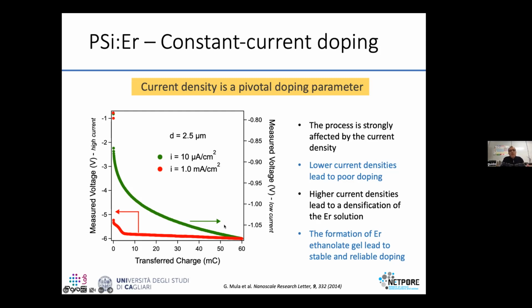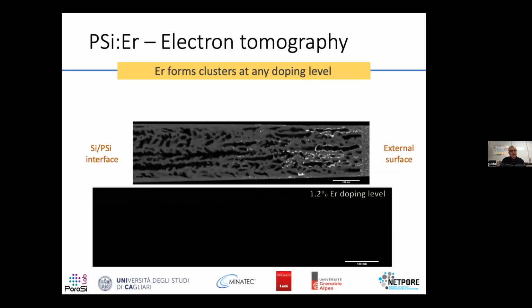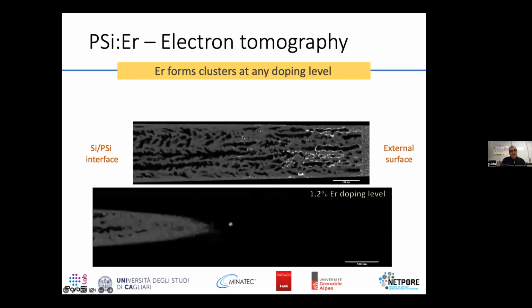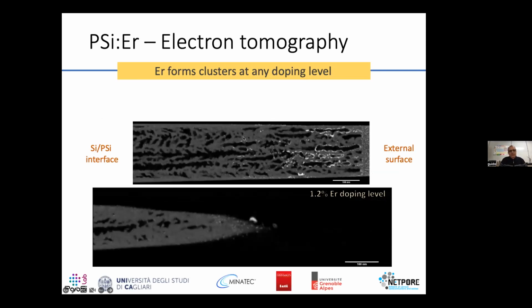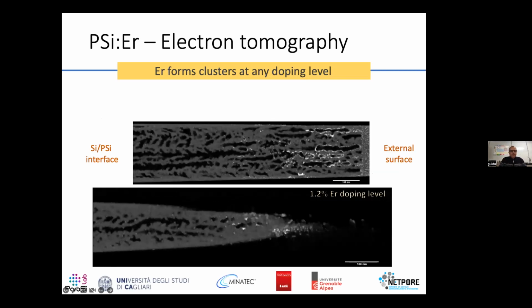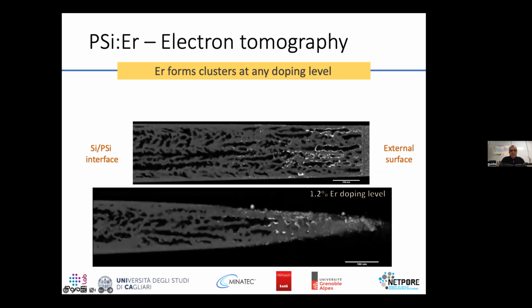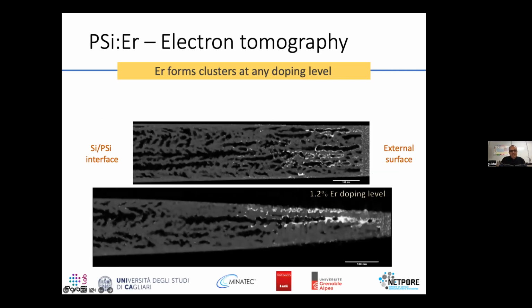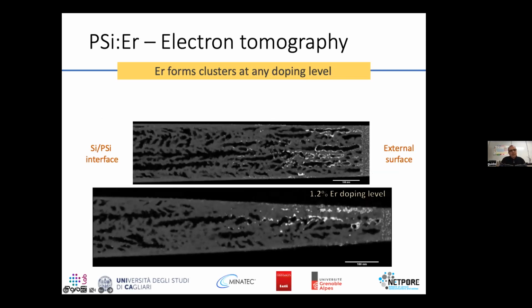So to understand how erbium is distributed on the surface, we resorted to electron tomography. And here we can see the white part, which is erbium, and the gray part, which is the silicon structure. And you see that there is a gradient, which is typical, unfortunately, in tiny pores.